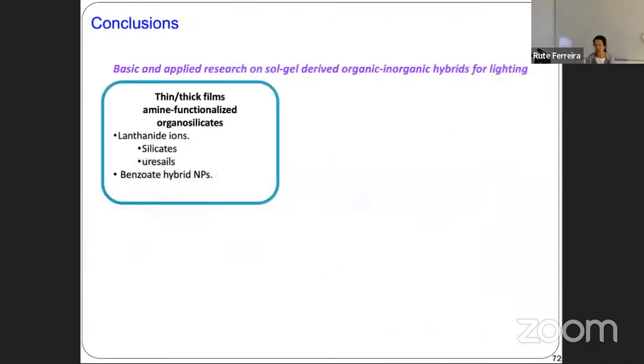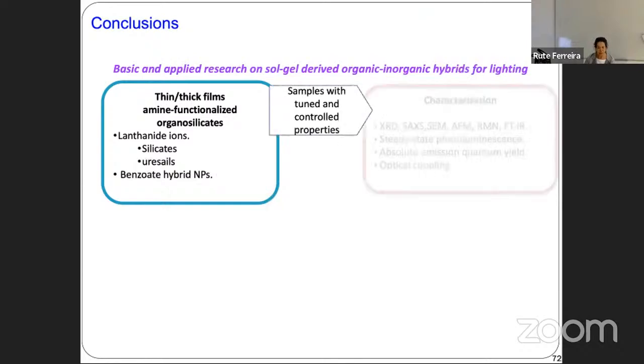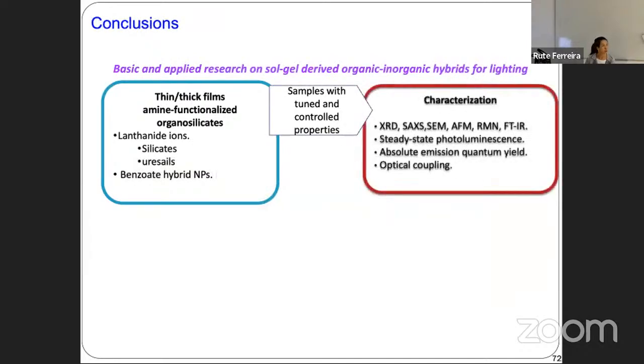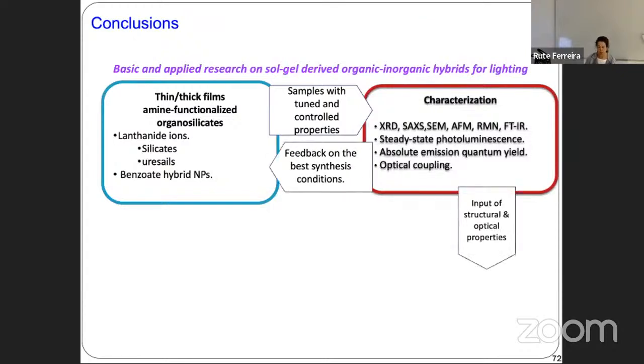So concluding, and I have to say here that, of course, I focused today on some prototypes, but of course, there is a systematic work, and this is only the result of some of the optimized samples. Typically, what we do is basic and applied research on sol-gel derived organic and inorganic hybrids for lighting. Here, I reported to you lanthanide ions incorporated into silicates and ureasils, and benzoate hybrid nanoparticles. Typically, the samples are characterized from the structural, morphological, and optical point of view so that we are able to feed back to the synthesis.